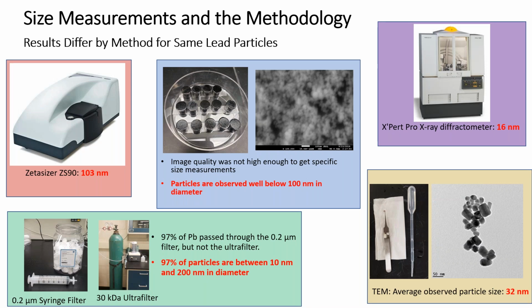So just expanding on that, size measurements. We have different ways we could take size measurements of particles. For those of you familiar with zeta potential or electrophoretic mobility, there's an instrument that uses a dynamic light scattering approach to also size particles. I'm going to show you results from the same suspensions, and the different results you get depending on what approach you use. This instrument uses a laser shot through a particle suspension, and it uses the distortion of the laser as the particles move through Brownian motion, and that distortion is converted to a size. So this suspension, the result is 103 nanometers.